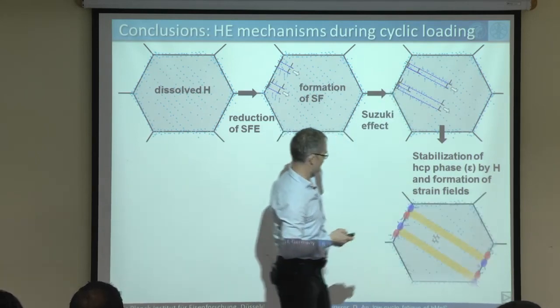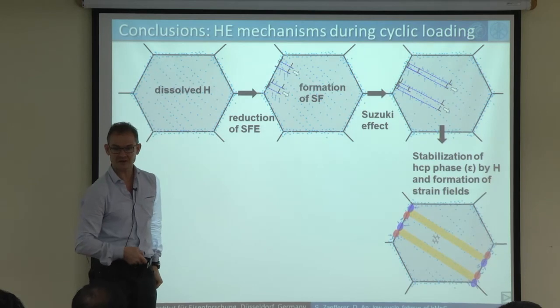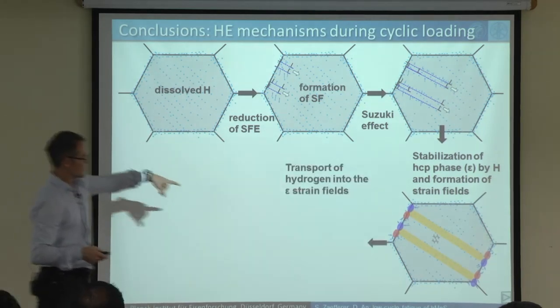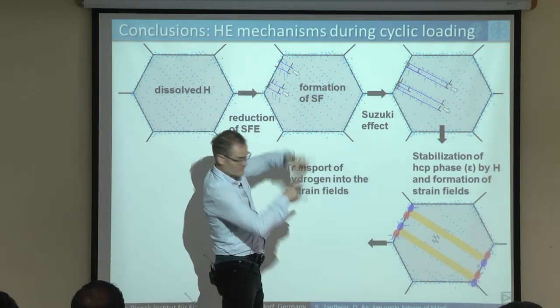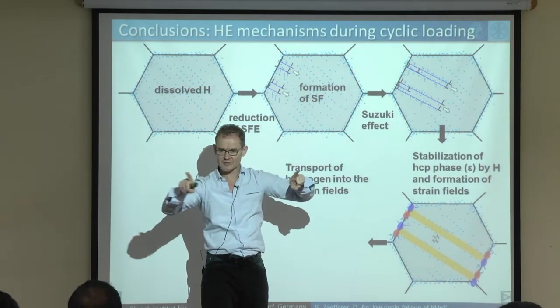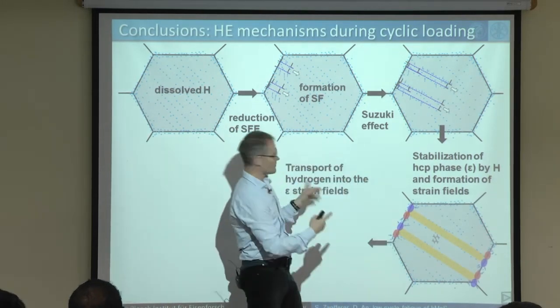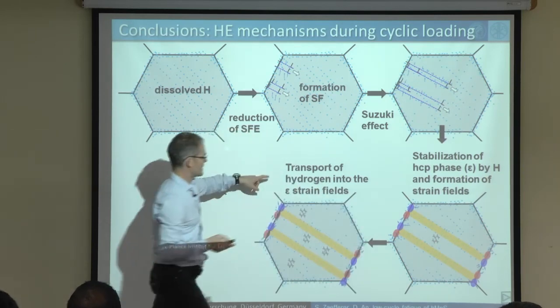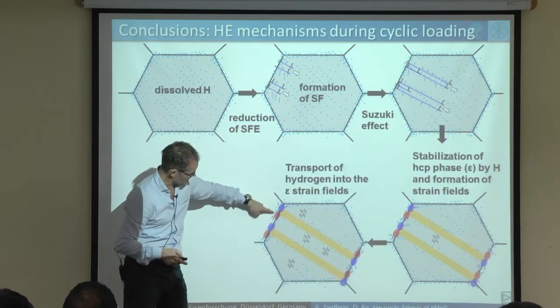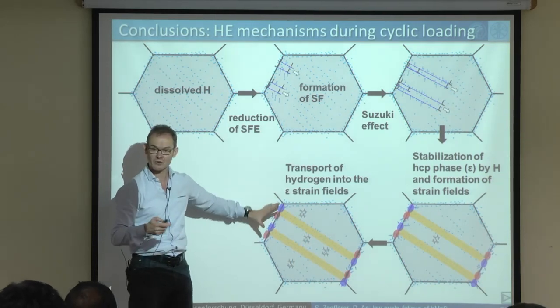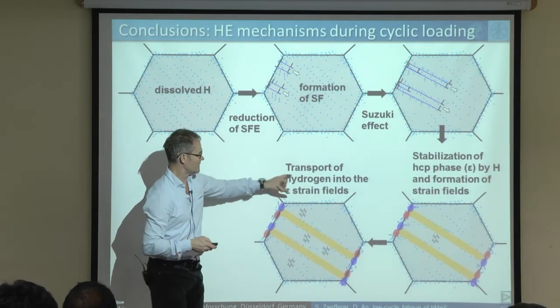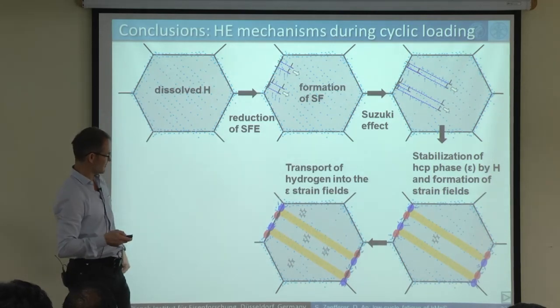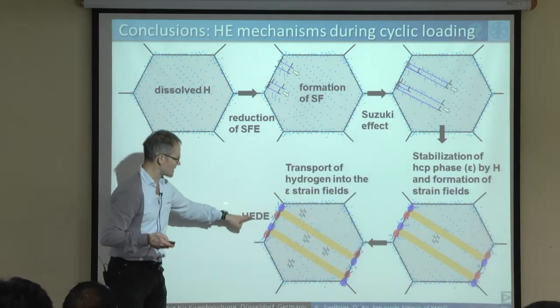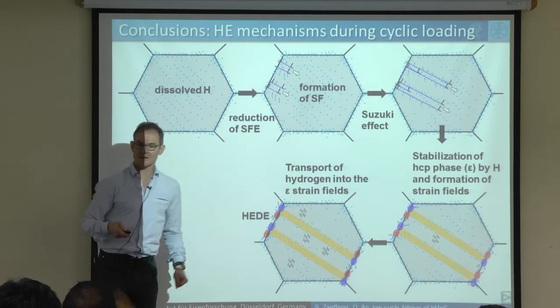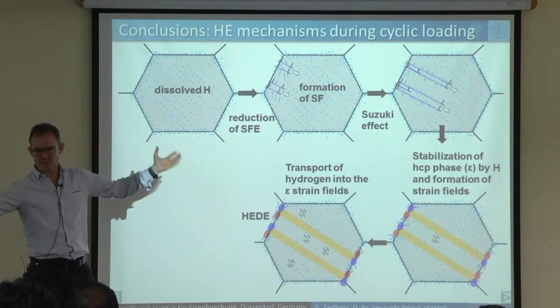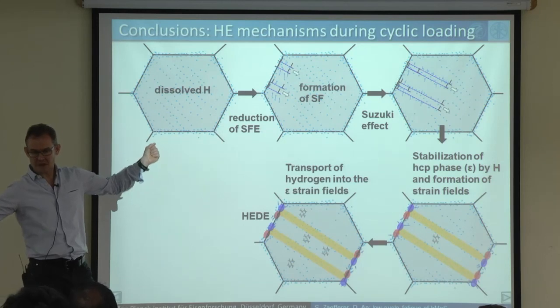So out of these stacking faults we are forming epsilon martensite. And because we have a back and forth movement during fatigue, this epsilon martensite continues to transport hydrogen to the grain boundaries. The hydrogen then goes into the strain field of the epsilon martensite and collects there, and that leads to hydrogen enhanced decohesion. So the grain boundary becomes weak and breaks up.